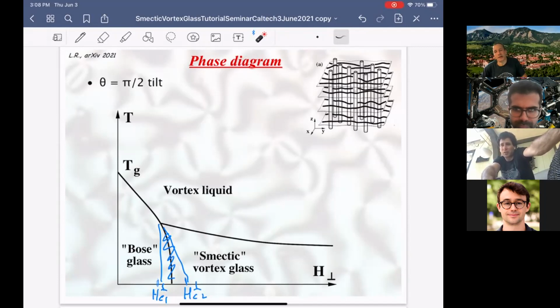Yeah, it's not really mixed. I think it's a fully bulk state. It's not just coexistence of anything. So there's no instability to phase separation, I guess? No, if I'm strictly deep in the type 2 limit, there's no instability. The only thing I'm saying is very simple. Columns distort things in this direction, but they do nothing along Z, along their direction. And therefore you get periodic order here. Of course, you can melt that periodic order with temperature and go to a liquid state. But you also want to understand the state first.